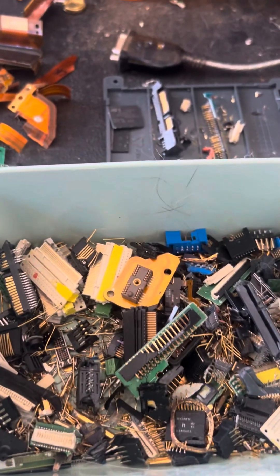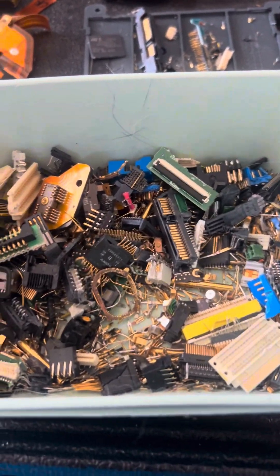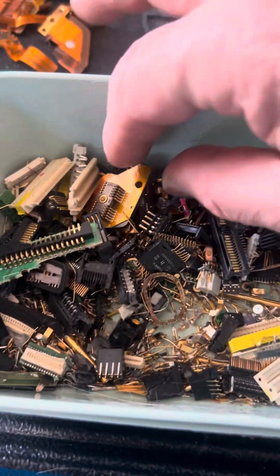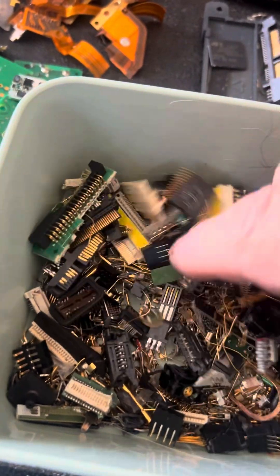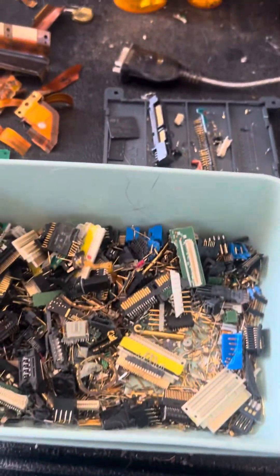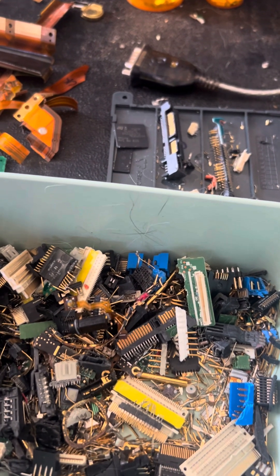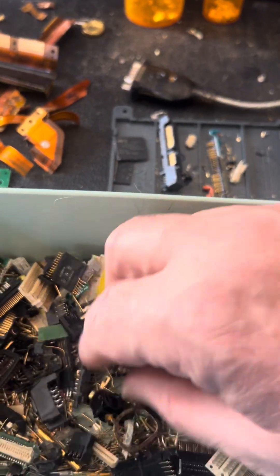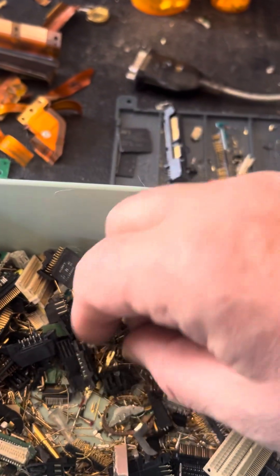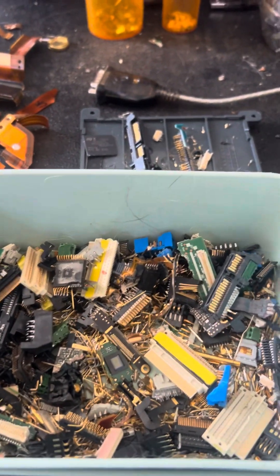This stuff came from my laptops that my father-in-law did — some recent pickups that are just ordinary e-waste. What I did was separate into a couple of piles. This obviously needs further processing. If they don't have wire on them, I feel like I'm safe enough to run them through acid peroxide. But prior to that, I'm going to dunk them in some hydrochloric acid for a couple of days to go after the solder and then run it through AP. I feel like that's the best way to attack base metals and the tin.